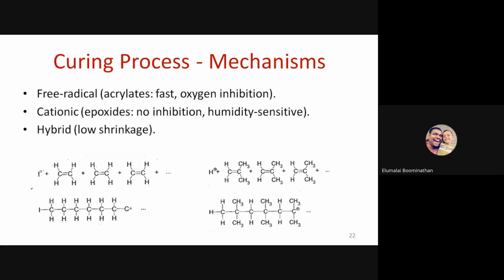But the free radical polymerization is generally used in acrylate systems. They are usually rapid curing, but they have a problem of oxygen inhibition. That means the oxygen surrounding the polymer will slow down the polymerization reaction or slow down the solidification. Cationic polymerization, which is usually used in epoxides, doesn't have this oxygen inhibition issue, but it is very sensitive to humidity and very slow in